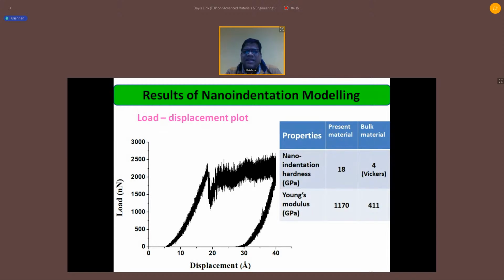The Young modulus value is basically an effective Young modulus value, because if we multiply the Poisson ratio of the indenter, that is a rigid indenter, so 1 by infinity equals 0, there is no need to add it. If we add the material's Young modulus, then the Young modulus is quite less. So here we present 1170 GPa, and it may be reduced. So we can say this Young modulus is a reduced Young modulus.